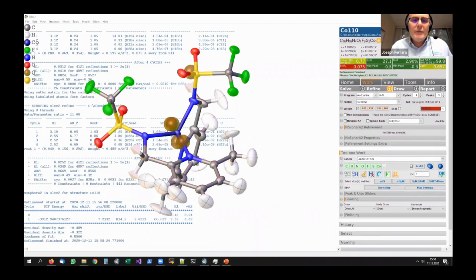Since the refinement moves to consider the asphericity of the electron density, have you considered introducing refinement of anharmonicity in the atomic displacements? What you will need to consider if you want to refine anharmonicity is that you will need excellent, brilliant, high quality, high resolution data to do so. If you refine anharmonicity on a, let's say, standard resolution data set, you will most likely swallow up unmodeled effects of, for example, absorption or other properties that are not modeled so far. Therefore, I would be careful to refine anharmonicity right away. You need a very good physical basis and a very good high resolution data set in order to do this.